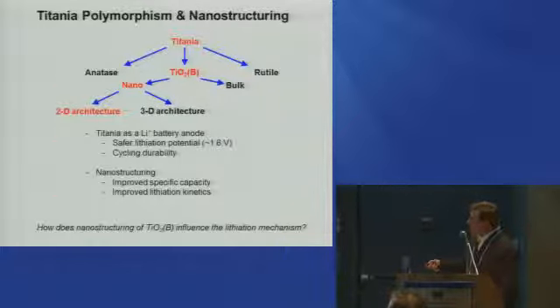So we can then think about not only the size and the shape, but also the architecture, making interpenetrating mesoporous networks. Titania, from a lithium-ion battery standpoint, has always been of interest for a long time, but in the bulk form, it doesn't do very well in terms of the reaction with lithium. But by going to nanostructuring, it was predicted that you could access a higher, kinetically stable lithiated phase. And so we wanted to actually show what the design rules were by controlling these material sizes and morphologies for this new polymorph.